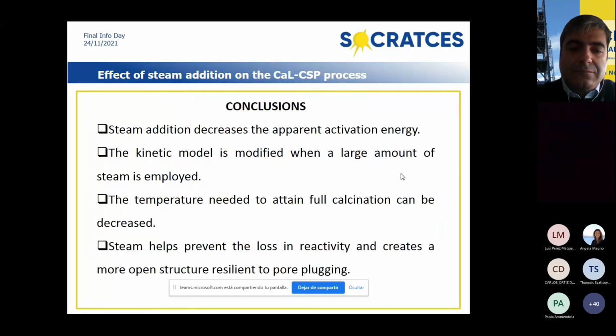So, we can say that steam addition decreases the apparent activation energy, and that the kinetic model is modified when a large amount of steam is employed. The temperature needed to attain full calcination can be decreased. Steam helps prevent the loss of reactivity and creates a more open structure, resilient to pore plugging. Thank you very much for your attention.